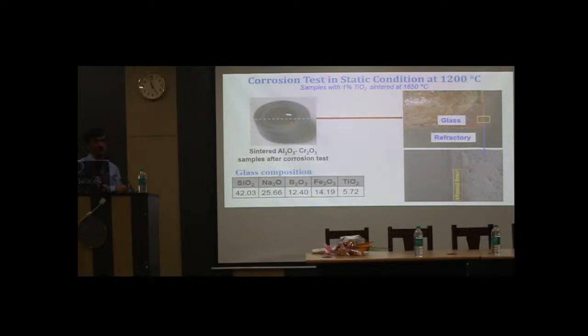We kept this glass and melted it at 1200 degrees centigrade for some time. Initially, this one is for 1 hour or 2 hours. Then again, you see the interface. The interface is a nice and clean interface. Apparently there is no visible corrosion, but under the microscope you see there is a corroded zone. Now we want to go in depth.